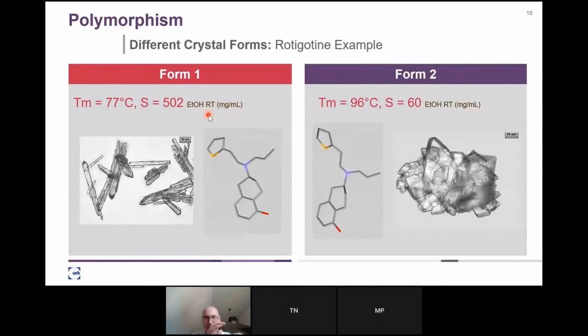But when the product was already on the market, then a second form appeared. Despite studies that had been done before, I have to admit that this was before my time, but apart from that, a second form popped up. So rotigotine suddenly started to crystallize in another arrangement in the crystal. You can see that the molecule had a slightly different type of conformation. And this allowed it then to crystallize in a different manner and in a manner that was more stable. You see it also forms another morphology of crystals. It is more chunk-like, blocky-like. And the melting temperature was 20 degrees higher than the previous one. And because it's more stable also, its solubility goes down because the crystals don't have a tendency to go again into solution as form one did. So this was a big shock, and it is a bigger story than this, but in the end we needed to withdraw the product for some time from the market in order to solve this issue.